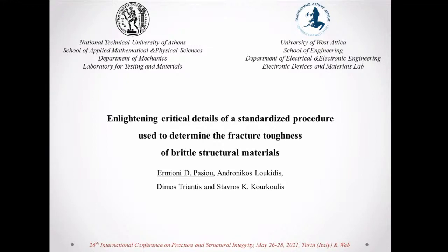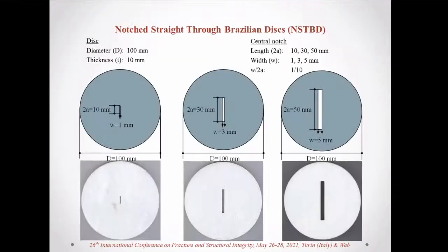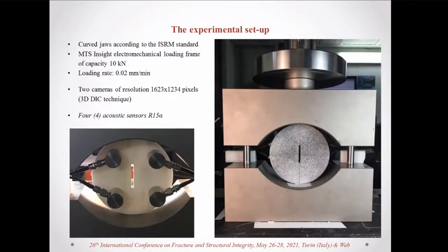Okay. Good afternoon, ladies and gentlemen. The present study describes a purely experimental protocol aiming to enlighten some critical details of a standardized procedure usually used to determine the fracture toughness of brittle structural materials. Notched straight through Brazilian discs made of Dionysos marble with a central notch were studied. The front surface of the discs was monitored by the two cameras of the 3D DIC technique used during the whole loading procedure, and 4 acoustic sensors were attached at the rear face of some specimens.